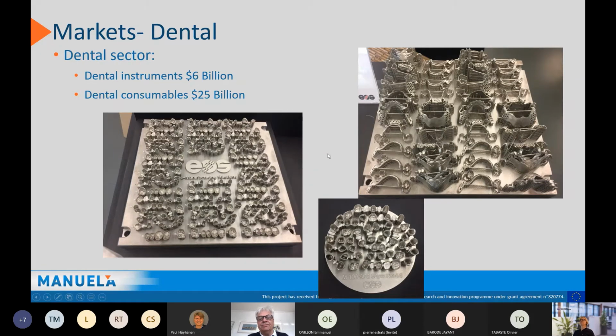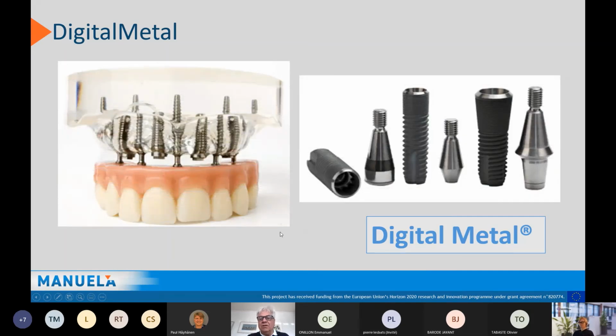Okay, next. Another thing you have is Digital Metal, in Sweden. This is not powder bed fusion, it's binder jetting technology where you can go much finer in dimensions. It's a two-step process where you first do your printing with the binder, remove the binder, and then a second stage process where you sinter the material together to the necessary density. It has certain pros and cons, but the key point is that you're using much finer powder, normally sub 20 microns. So the surface finish and the products that you can create are on a different scale. Next slide.